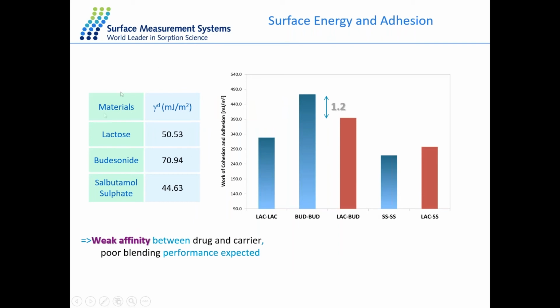So this is a result of the dispersive surface energy of each of our materials. And what we can see is that the budesonide has a higher dispersive surface energy than the other two components. What we can also plot is the work of cohesion and adhesion. So in this case, we want to understand the affinity between the excipient and the drug molecules.